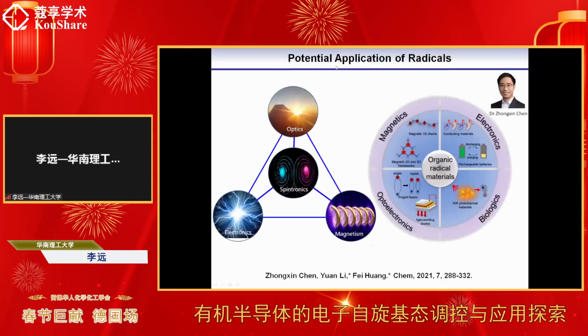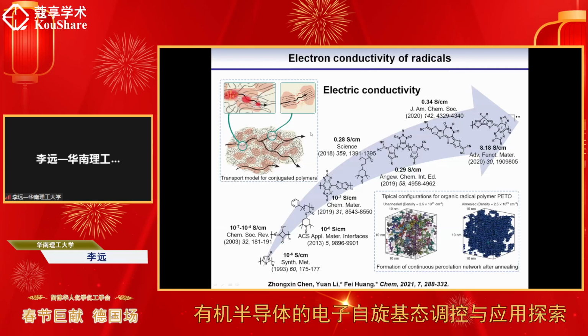And in this slide, I will show you the potential applications for radicals. There are many applications in magnetics, electronics, biologics, and for example, I will show you the radicals in the field of electroconductivity. We can see that we introduce the radicals into the polymers or small molecules. We can enhance the electroconductivity to a very high level. You can see in this Science paper, the TEMPO-based polymer can achieve 0.28, which is a very high electron conductivity.